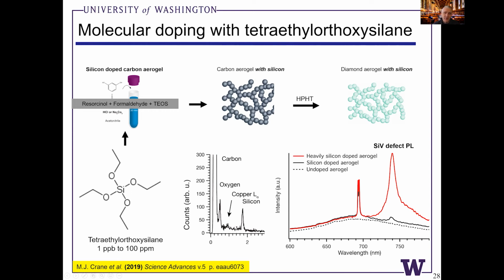in the undoped controls. But more excitingly, when we went through this high pressure, high temperature laser heating process, we could see huge amounts of silicon split vacancy emission from this material. And in comparison with a control undoped sample, there's no silicon doping. No silicon split vacancy emission, and we can vary this concentration with exquisite precision using parts per trillion, parts per billion doping levels up to parts per thousand. In the limit, you could even make a silicon carbide material, which is an interesting future direction to consider in terms of quantum information science.